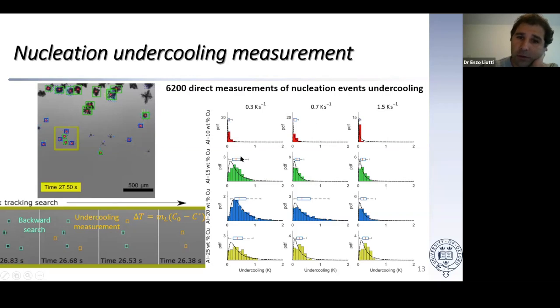But interestingly, for example, these undercooling curves essentially decrease with an increase in the cooling rate. This is actually not what is believed normally, in the sense that normally it's believed that the effect of cooling rate is that it increases the amount of undercooling and therefore you get more nucleation. What we actually show with this data is the opposite. You increase the cooling rate and nucleation happens at lower undercooling. And it will be clear later why.